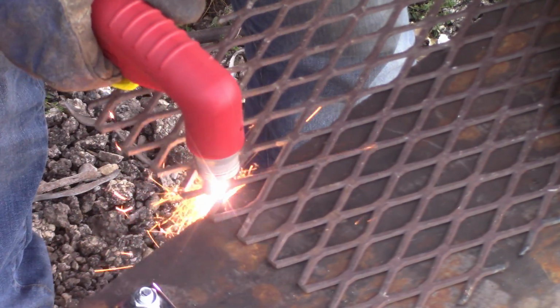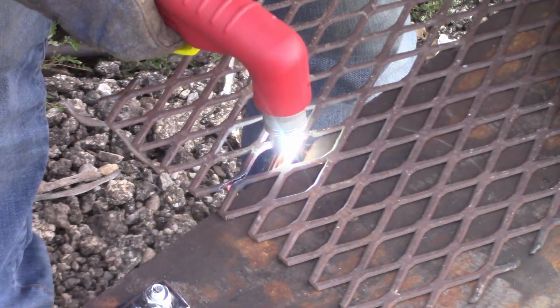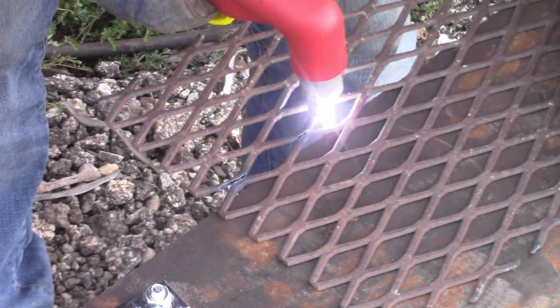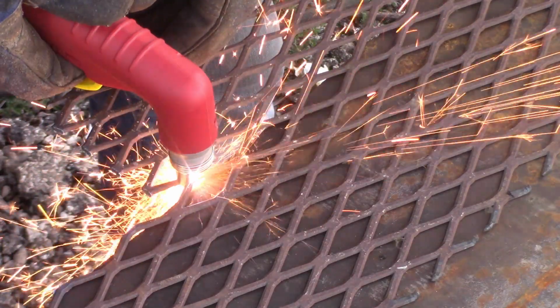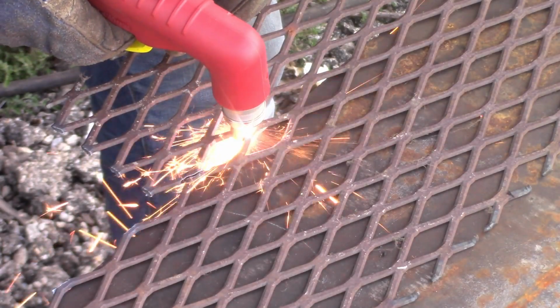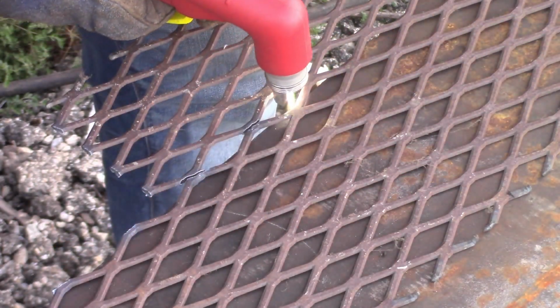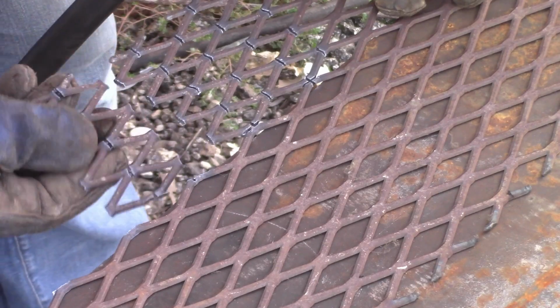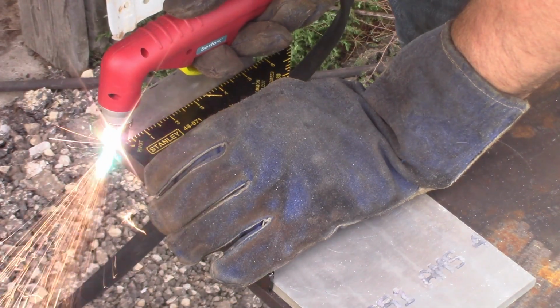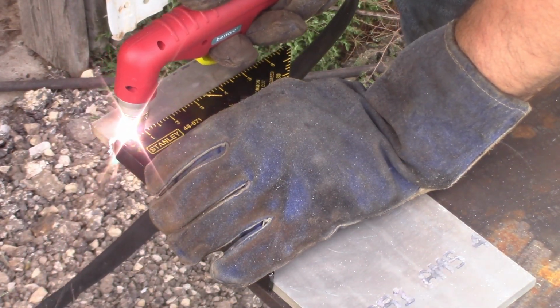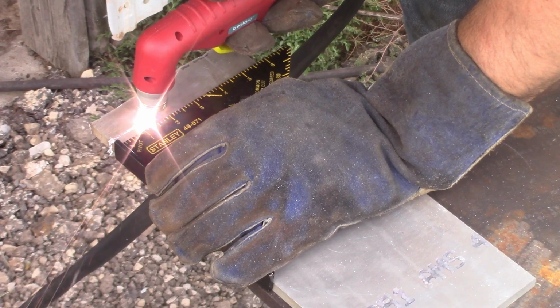I tested the mesh setting on the machine on some 1/8" thick expanded metal, and it works just as advertised. I cut this at 20 amps and 35 psi just like I did with the solid 1/8" material. What you're seeing here are not individual cuts. I'm leaving the trigger down and it restarts after passing over the voids in the metal. I don't work with expanded metal very often, but for those of you who do, I think you'll like this feature. Next up was some 3/8 or 10mm thick aluminum, which I cut at 40 amps and 50 psi.